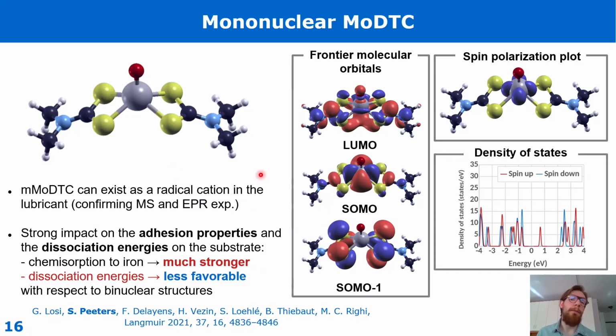Of course, neutral compounds can also be present in the lubricant mixture, and they might not be detected. And for this reason, we carried out our theoretical characterization by considering both the cationic and the neutral compounds. So the mononuclear radical cation has a much stronger chemisorption to iron and also less favorable dissociation energies compared to both the neutral compound and the binuclear structures. So here you can see, for example, the frontier molecular orbitals, and also the simulation can very well detect the localization of the radical electron on the molybdenum atom, and also it can be detected by the asymmetry of the spin components on the density of states.